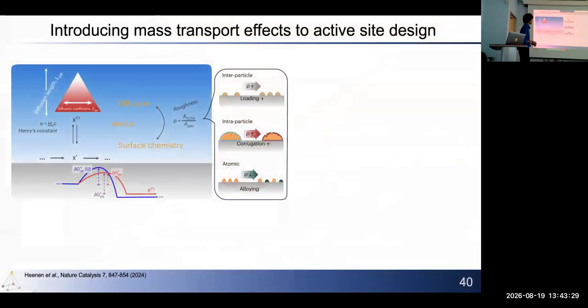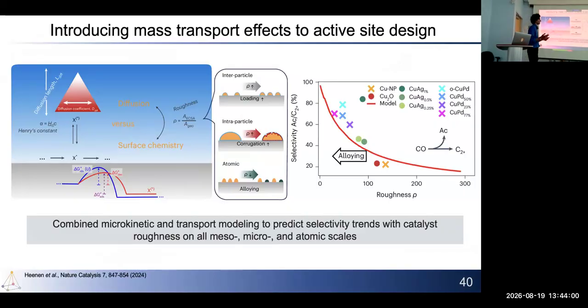Okay, and then finally, I'll talk about how we think about active sites beyond just the atomistic approach that I talked about. One area that I've been really interested in is working a little closer with our chemical engineering colleagues to bring in mass transport and diffusion effects to thinking about surface chemistry. So how do you integrate diffusion with the electronic structure approach that I've been talking about? I found this really interesting study where you can, for example, change the interparticle spacing or the interparticle roughness, and that leads to a change in how your selectivity metrics show up. You can quantify this using, for example, a roughness factor going all the way from atomic roughness to mesoscopic and macroscopic roughness, and then plug all of that into a single model to capture these effects. So this is one area that I'm really excited to go into.